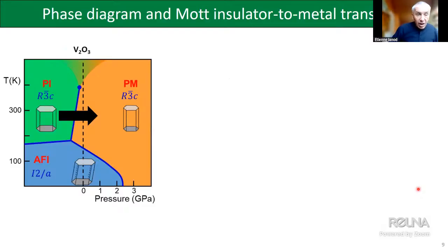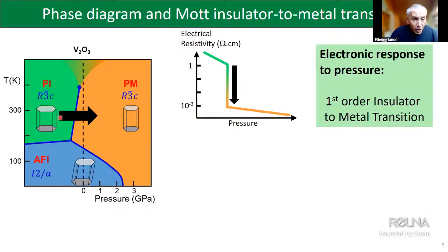All right. And just to illustrate the fact that the real phase diagram corresponds indeed to the one predicted by modern theories such as dynamical mean field theory. Here you have the phase diagram of the V2O3 system, and you recognize at room temperature two phases: PI, for paramagnetic insulator, meaning Mott insulator, and PM for paramagnetic metal, so it's metallic indeed. And you recognize in blue here, almost vertical, the Mott transition line between the Mott insulator and the metallic state. When we apply a pressure, we cross this line, and we have a drop of electrical resistivity by several orders of magnitude.